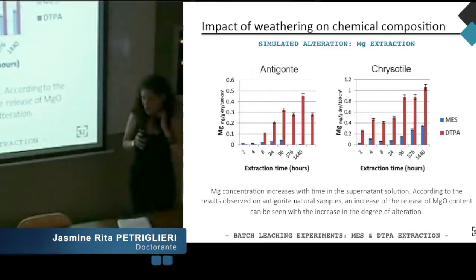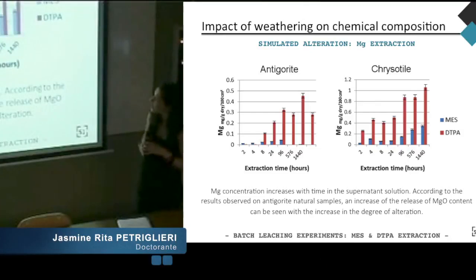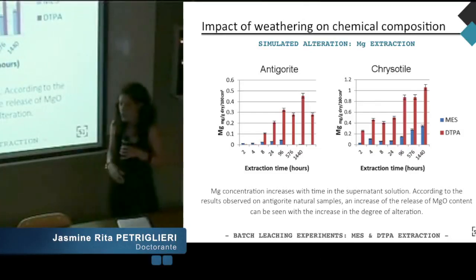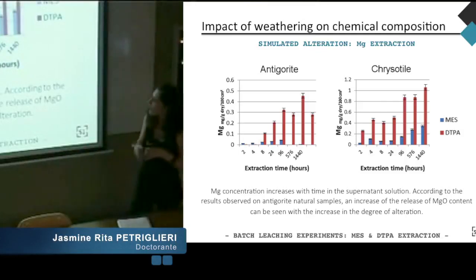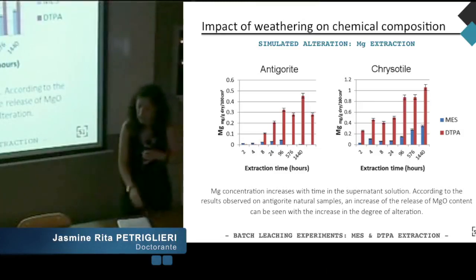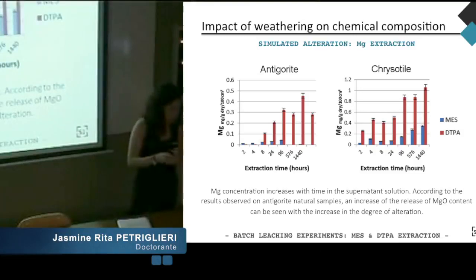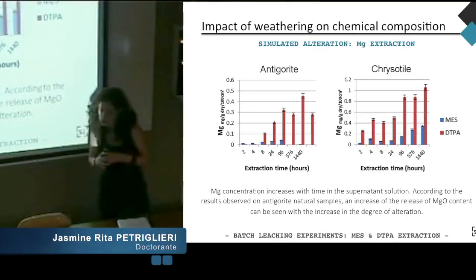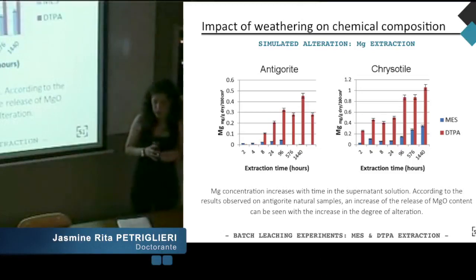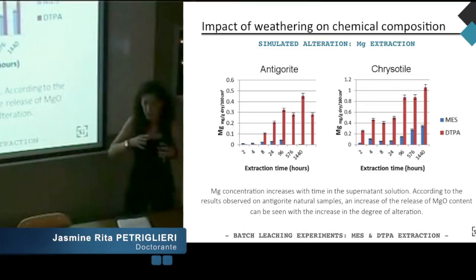So, two batch leaching experiments with MES and DTPA buffering solution extraction were carried out on samples classified as not altered, antigorite and chrysotile, in order to reproduce and to extract major elements. I report here the case of magnesium content, and magnesium concentration increased with time. Experiments were realized from 2 hours to 60 days, and we find a magnesium concentration higher in the solution. This result is in accordance with results observed on antigorite natural samples. An increase of the release of magnesium content can be seen with the increase in the degree of alteration.